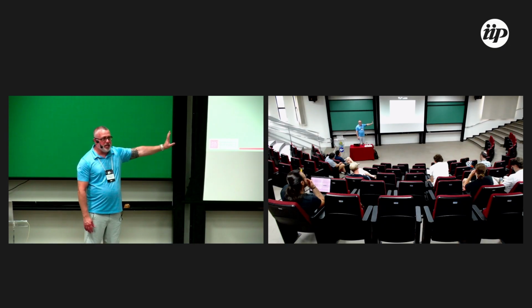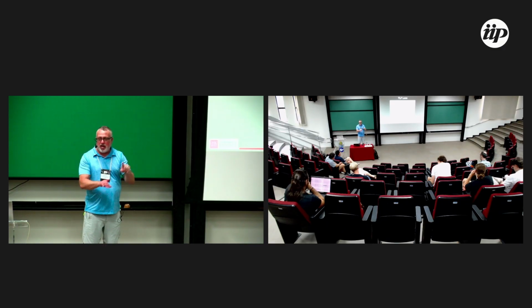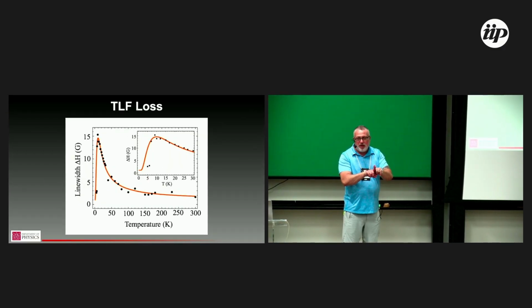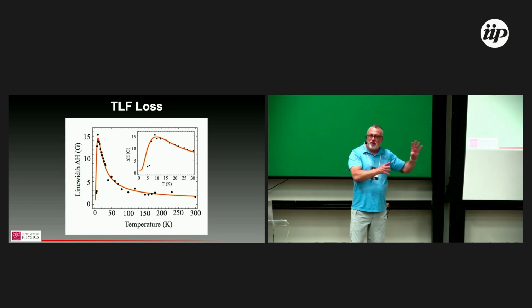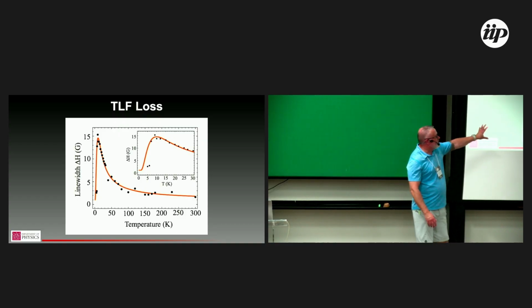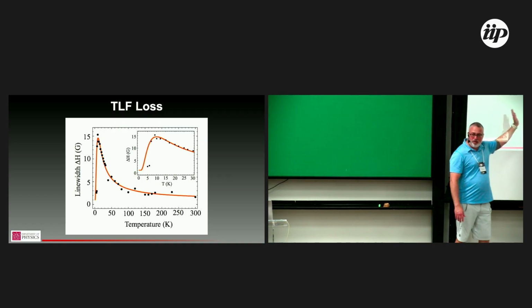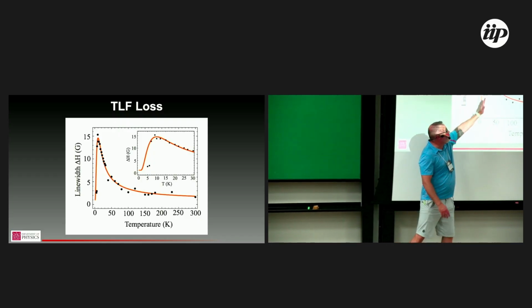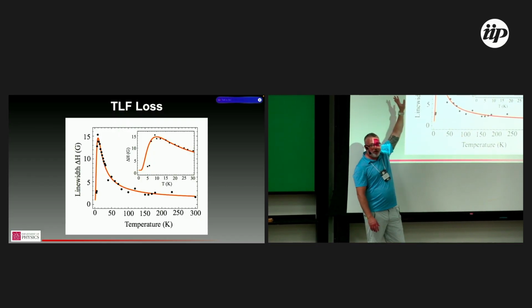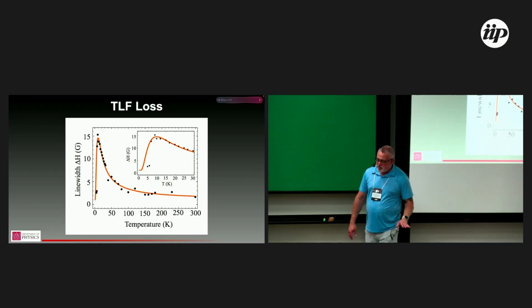line width is a particularly tricky parameter here because at a minimum we have spin wave modes, and the n=1 spin wave mode and the FMR mode are very close in this system. We may have other peaks from other things happening. So the difference between broadening and peak splitting can be hard to resolve in certain regimes. And so there's a lot that can be happening, which is why I've been a bit cagey about saying too much about what's happening in the low temperature and even below. I mean, I think if we start here and move up, the fact that we see the damping increase, that was perhaps my phone.